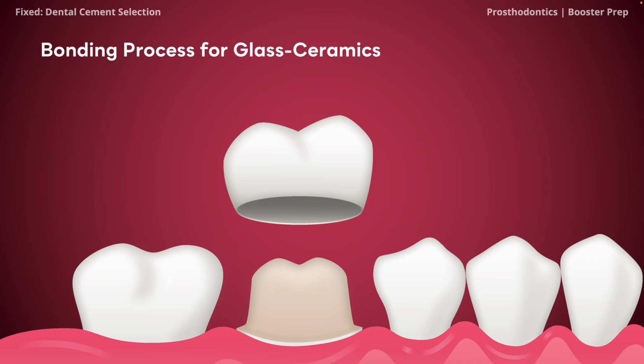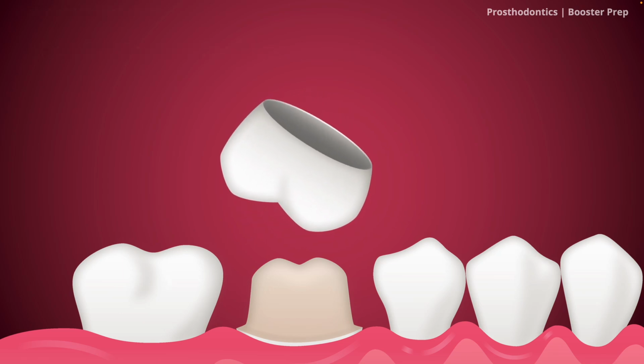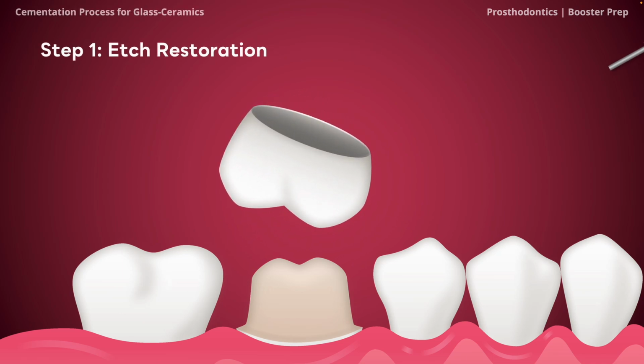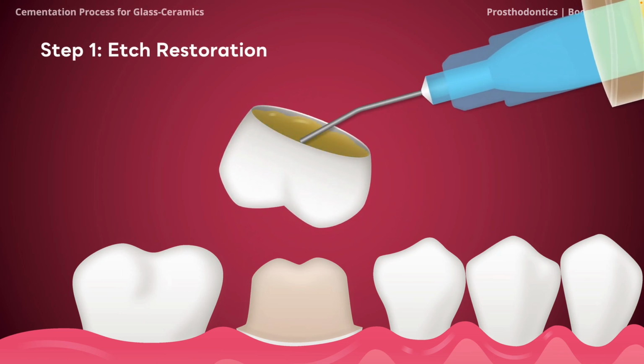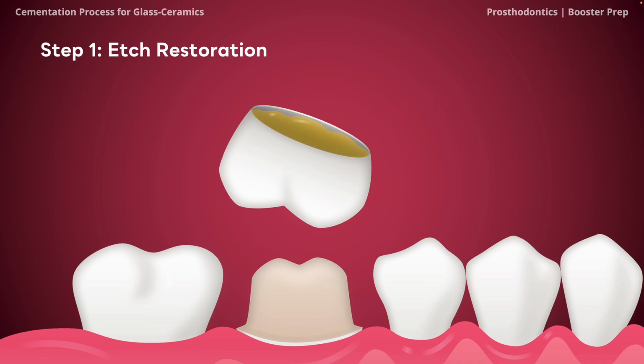The important thing you need to remember is that you need to etch and bond both the restoration and the tooth. First, we'll want to prepare the restoration itself, and it all begins with etch. This is typically done for 20 seconds with 5% hydrofluoric acid, which is strong stuff, so you've got to make sure you use it on the restoration, never the tooth. Next, you'll want to remove all the acid, which can be done by simply washing thoroughly with water and drying, or by placing the crown in an ultrasonic bath with some alcohol.